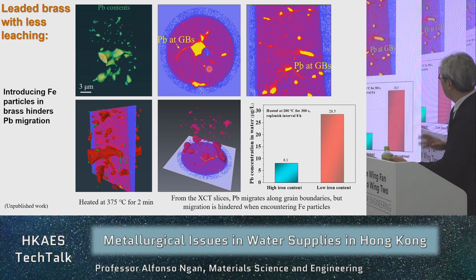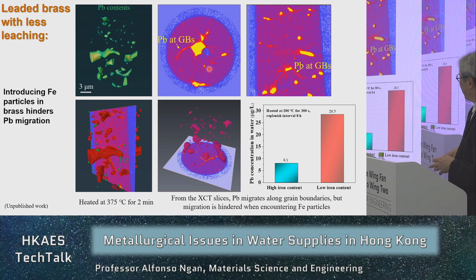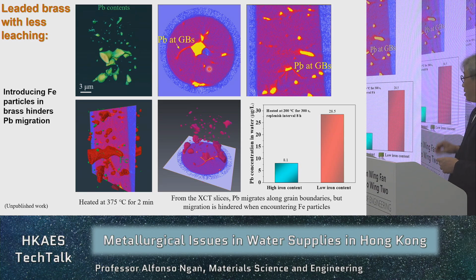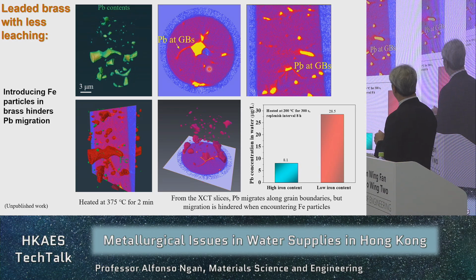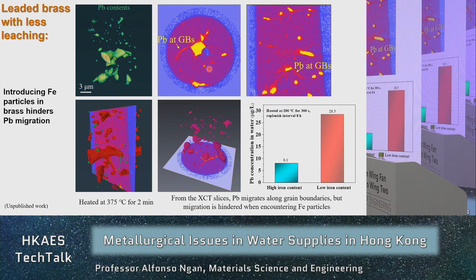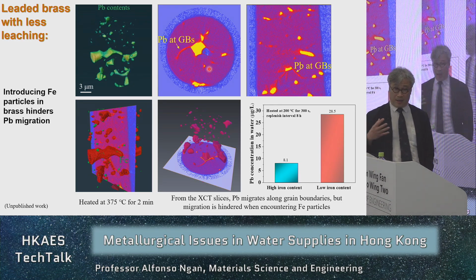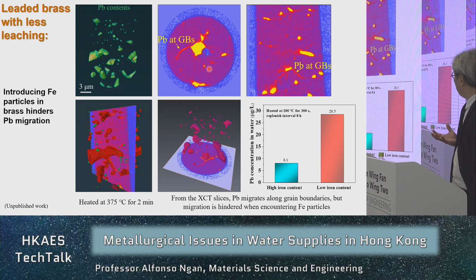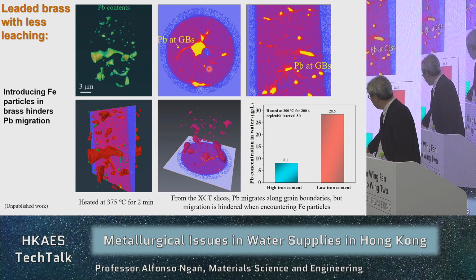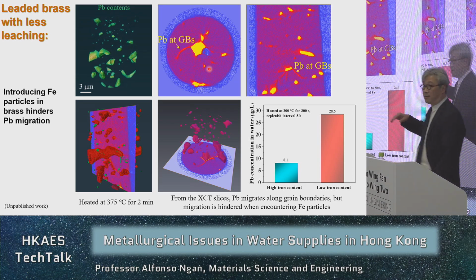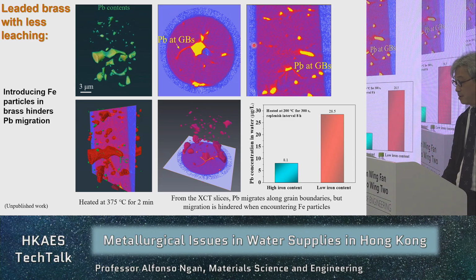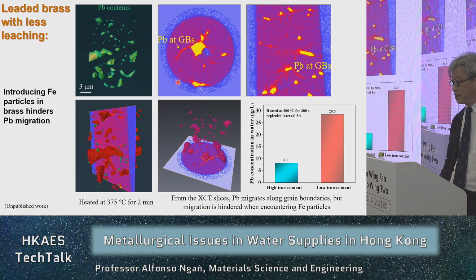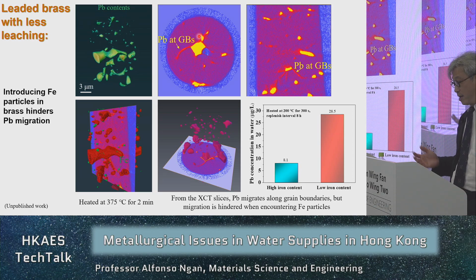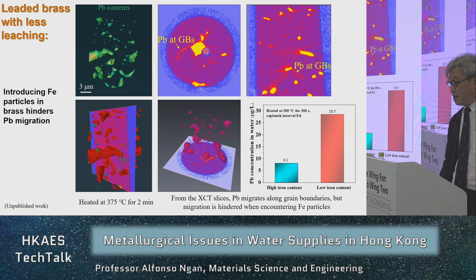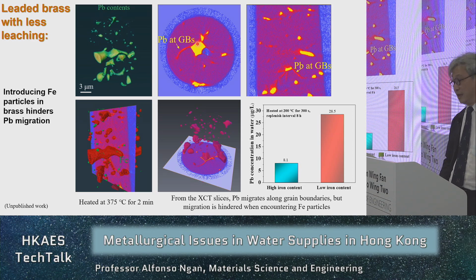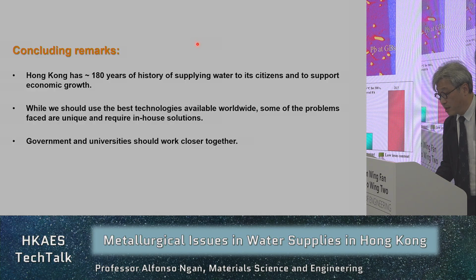The last slide now is also something that we are developing by one of our postdocs, Dr. G. He's looking at not pure brass with lead, but brass containing iron as well as lead. He found that when you have iron present, these green stuff, they are the iron, they will actually hold up the lead. So when the brass contains iron, the leaching is smaller. Again, this is something quite interesting. This could be a material that would still be useful for cutting, or for transporting water, but is more tolerant to leaching of lead. Okay, so that's my last slide.